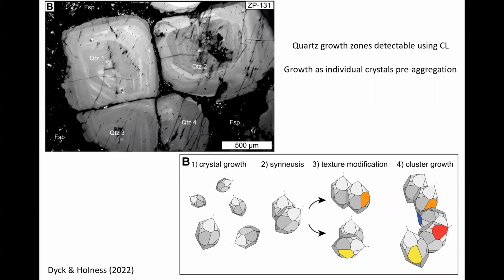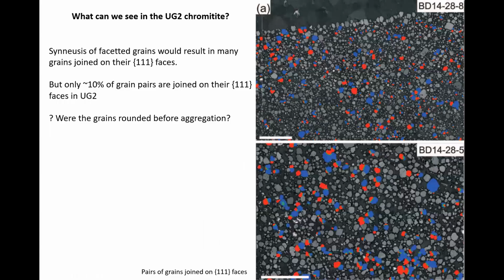You can also see them with quartz. This is a paper that Brendan Dyck wrote, where he was looking at the granites from Bushveld, and you can see clusters of quartz grains. And they've come together on growth faces and they've sintered to form clusters. And that was his argument, that we've got convection in that granitic system. And we can see the internal growth zones of the quartz using cathodoluminescence, so we can tell that they grew as separate grains and then came together to form clusters.